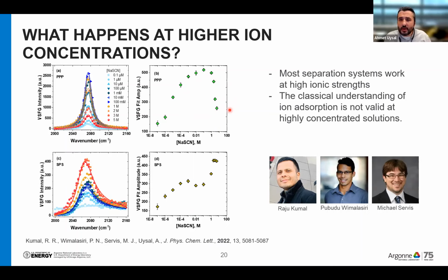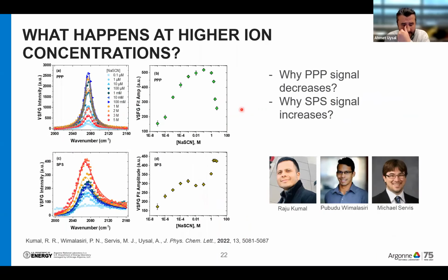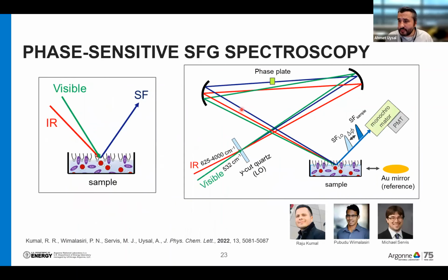To understand that, we cannot use classical SFG measurements, because we lose the phase information. Very similar to our X-ray experiments, there's a phase problem, and when you lose the phase, you cannot understand the orientation. But we can solve it in SFG by using phase-sensitive SFG experiments. And here I just show briefly how phase-sensitive SFG works.